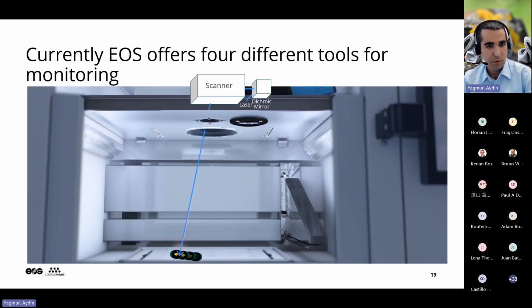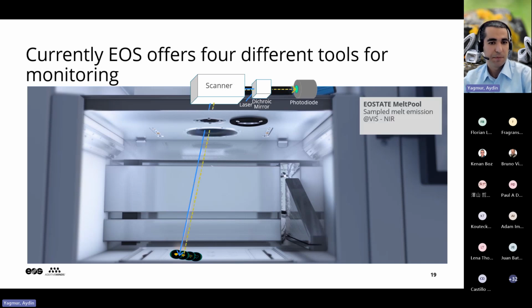This is the very first one, melt pool monitoring. This is an addition to the optical path, and it detects the intensity of the light. It is a photodiode. What does it mean? Photodiodes can record the intensity of a given wavelength, but they do not have location information. This information is taken from the scanner, and the images, which I will show in a few seconds, are created from the melt pool. So melt pool is getting information from the melt pool only. So you can analyze the stability of the laser exposure with melt pool.